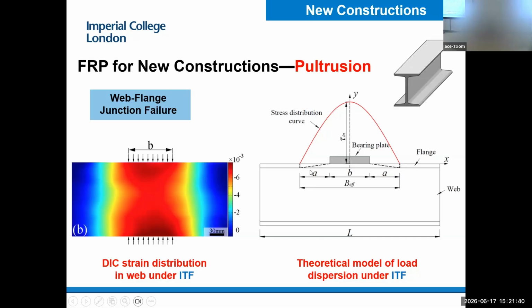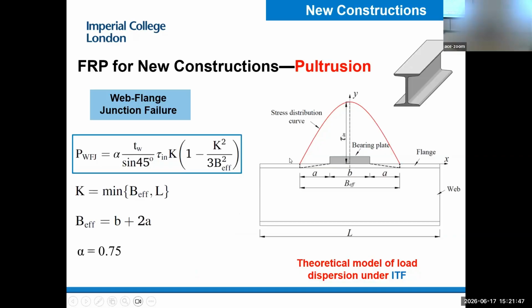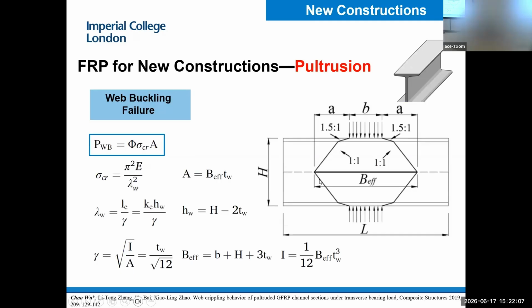Because the failure happens at the web-flange junction, all you need to do is integrate the stress along the fracture surface. You do stress integration along the fracture surface to get the fracture load at the web-flange junction. Also, if the web-flange junction is strong enough and doesn't fail, the load will be transferred to the web.